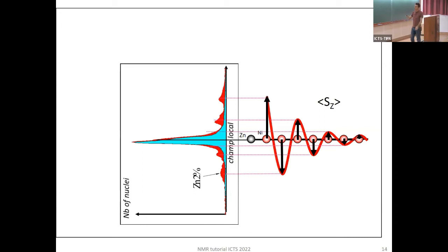So what happens, it's very interesting. It's a correlated system. So imagine you have a very standard paramagnetic system with no correlation. You remove one spin. Well, nothing happens. The rest of the spins just don't respond. But in a correlated system, it's not like that. You remove one spin, the system has a correlation length, it will try to screen your defect somehow. And the way it responds to this vacancy in the spin one chain is by developing a staggered magnetization like that in the vicinity of your defect.